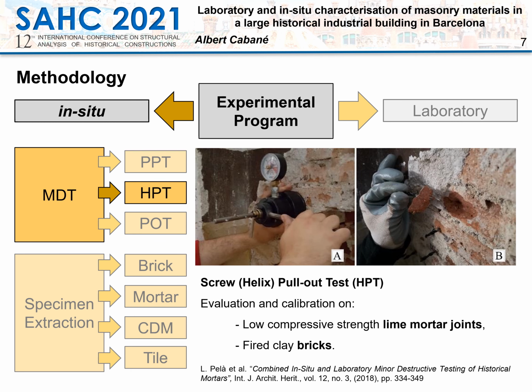The second minor destructive technique was the screw helix pull-out test, executed on the same 6 zones of masonry walls to evaluate the mortar joint and the brick components. This test allows to measure the pull-out maximum force reached by a high-strength steel helical tie. The pull-out force is used to characterize the material tangential stress. This test could be found in previous research developed at UPC, usually executed on mortar joints.